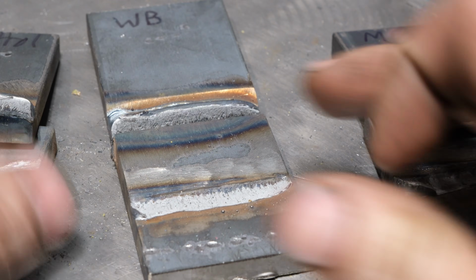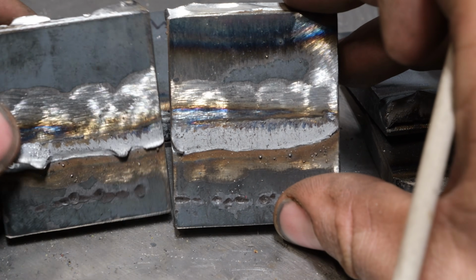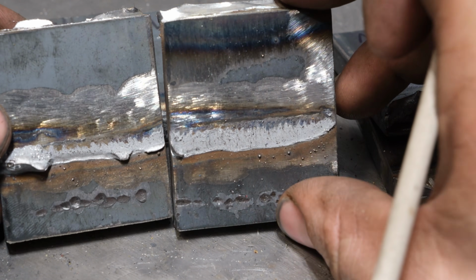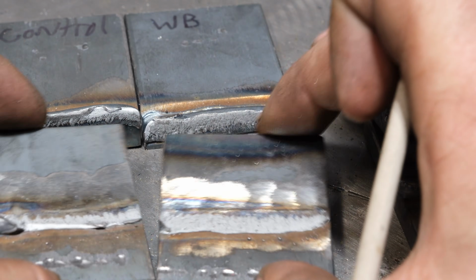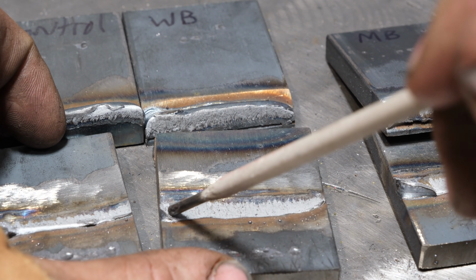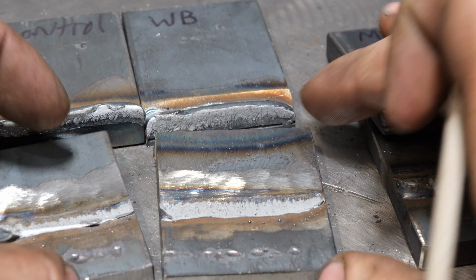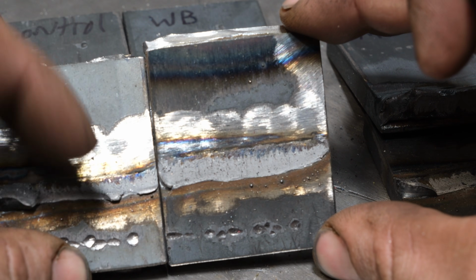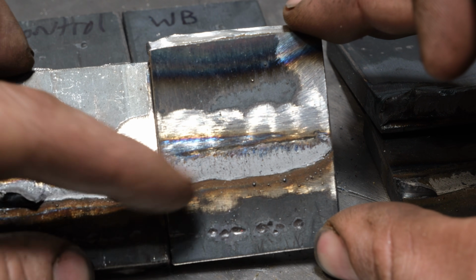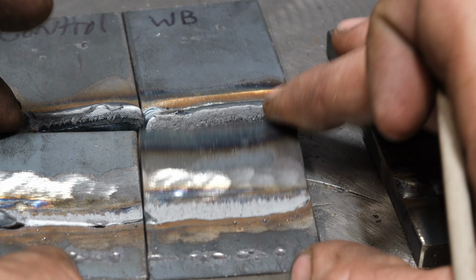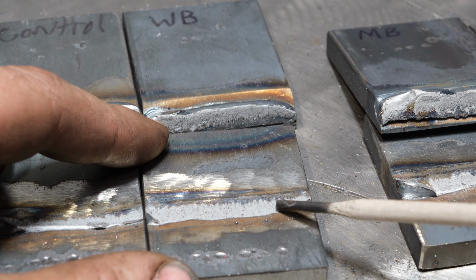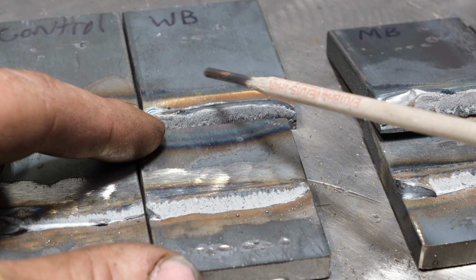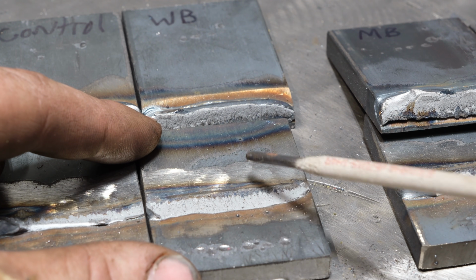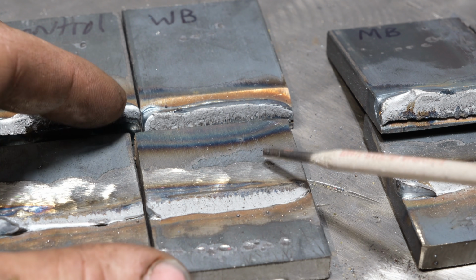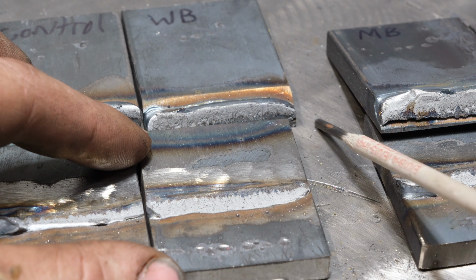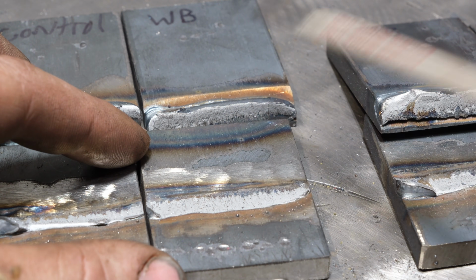One thing, you look at these two, see how much more bite into the bottom plate? And part of that could be the angle that the wire was coming in, putting more heat here, but that's a better result. When you start seeing stuff like this, you've got issues. This one, nice and wide, you knew it bit in some, but it completely broke off the bottom plate, likely because it had more fusion into the top plate, which would be expected because the bevel is going to melt this easier than this because of the heat input.